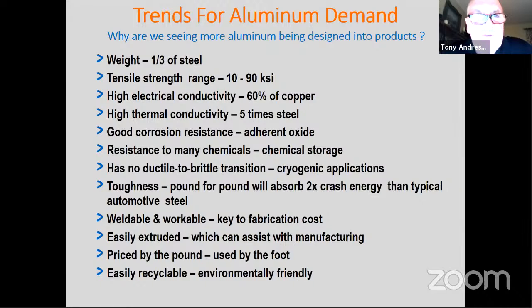In terms of the material itself, it has a wide range of strength. So we have a great selection of different alloys that might fit different applications. We get some of the very low strength alloys like the 1000 series, the commercially pure aluminums, which are typically not used in structural applications, but are used for other reasons like electrical conductivity and corrosion resistance. But they don't have very great strength. Then at the other end of the range, we have some of the heat treatable alloys that get in excess of 90 KSI. Some of the materials used in the aerospace industry, the 2000 series and the 7000 series, the copper-based alloys and the zinc-based alloys, have great strength in certain heat-treated conditions, in certain tempers. So there's a wide selection in terms of design criteria.